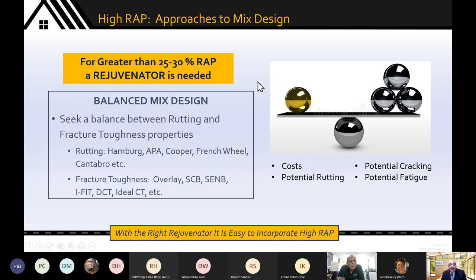So you tend to fall back on what's known as balanced mix design. In balanced mix design, you're looking to seek a compromise, an optimum point between two competing properties, how stiff it is versus how soft it is. The stiffer it is, the much better it is in rutting properties, but it's quite poor in crack resistance, fatigue resistance, damage tolerance type situations. If it's too soft, it has very good damage tolerance properties, but the material may have a tendency to rut or ravel. How do you measure these properties for rutting?